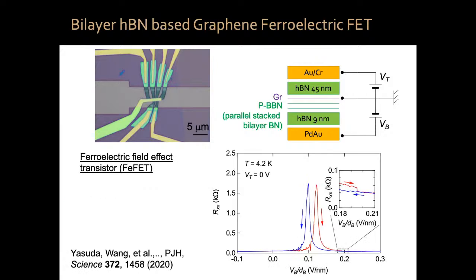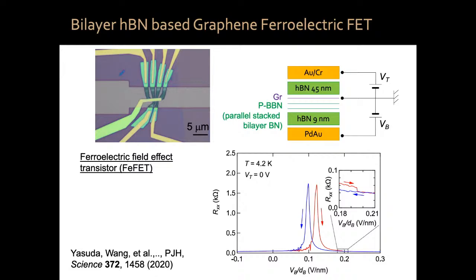So when you measure the resistance versus electric field for such a device, remember that I told you the conductance has a V shape for graphene. Resistance, which is 1 over conductance, looks like a peak. The opposite, 1 over a V shape, which is a mountain. So if you sweep the electric field in one direction, you have this maximum and then like this. If you reverse and sweep in the opposite direction, you have the same thing, but shifted. You have hysteresis. And that hysteresis is the signature of this ferroelectric behavior.